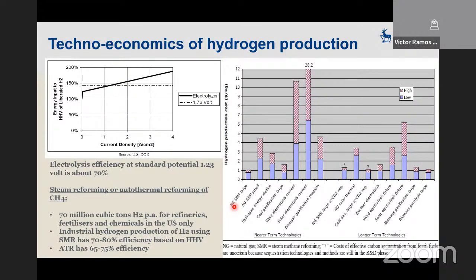The technical economics of hydrogen production is very clear. At the moment, green hydrogen, that is to convert solar, wind, and other renewables to hydrogen, is about $3 to $6 per kilogram of hydrogen. Where gray hydrogen, where you convert methane into hydrogen, is about $1 to $2. $1 to $2 is commercial value. Now it's produced for chemical industries and for other uses already. So this is the natural gas steam reforming route. But if you use biomass, it's even higher cost. Biomass conversion to hydrogen is prohibitively expensive.